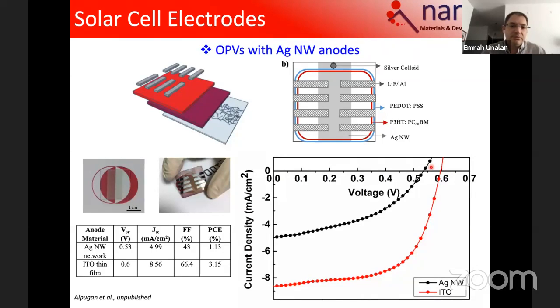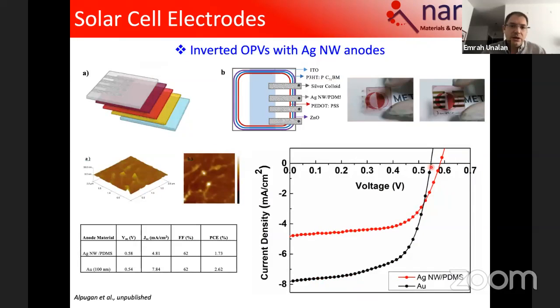And not only silicon-based solar cells, we apply this idea to organic photovoltaics. And the benefits are, on the right-hand side, as you see, you have a typical aluminum top electrode, or it can be gold, but it's just literally blocking the light. But if you have silver nanowires, the device becomes semi-transparent, so you can shine the light from both ways. And we are now expanding this concept into perovskite and silicon perovskite tandem solar cells.